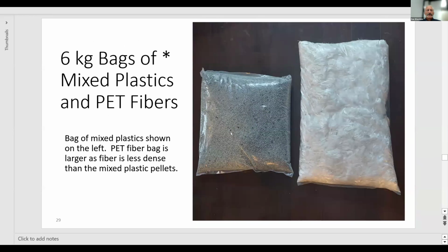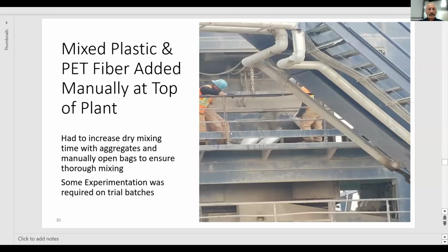Here's a mixed bag of plastics shown on the left. The PET fiber bag is larger as fiber is less dense than plastic pellets. The mixed plastic and PET fiber were added manually at the top of the plant. We had to increase dry mixing time with aggregates and manually open the bags first to ensure thorough mixing. So some experimentation was required on trial batches.